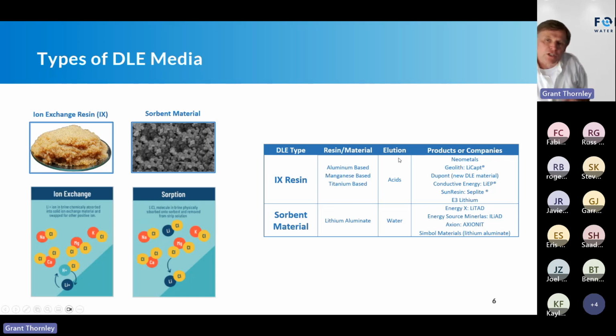To elute, once you've loaded up the lithium, I've got to unload the lithium. So you're going to elute that with a reagent. Typically in ion exchange, you're going to use acids. The uniqueness with sorbent material is that I can typically use water to elute the lithium off. So in some cases a sorbent material may be preferential over an ion exchange, or vice versa, depending on where you are. There are lots and lots of DLE media suppliers out there. These are just a small fraction of them.